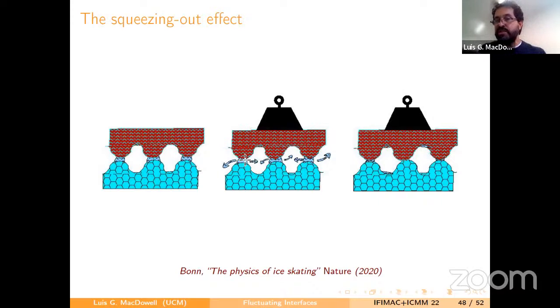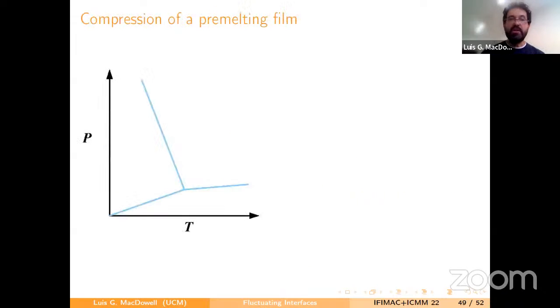It's nice that it has a low viscosity, but it can be very easily squeezed out. And when it's squeezed out, then you are left with the bare contact and you get large friction. So he argued the pre-melting film cannot be the reason for the low friction phase. But you know, you need to take off your tribologist suit and put your water expert suit on and take a look at the phase diagram of water.